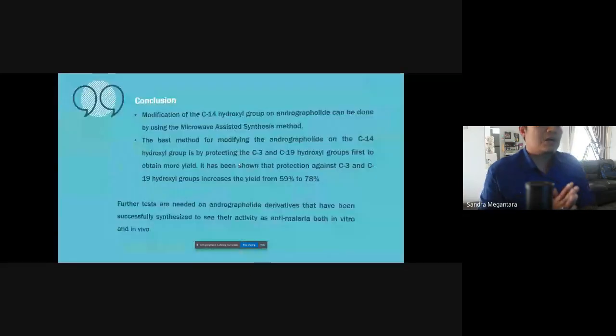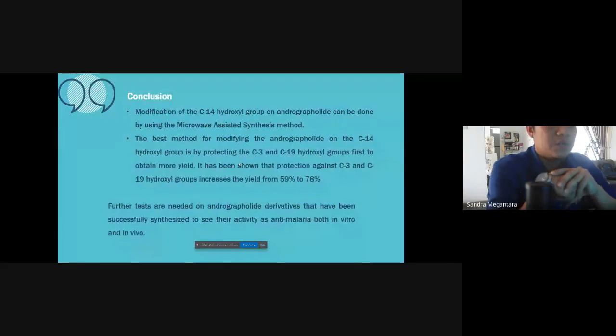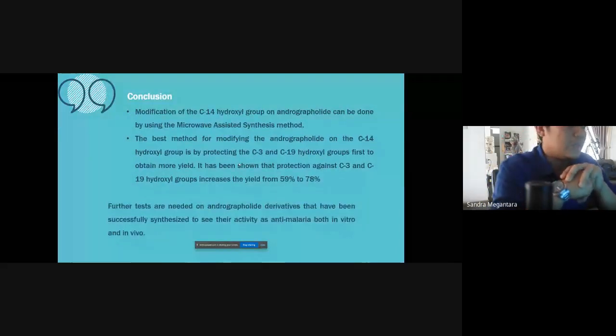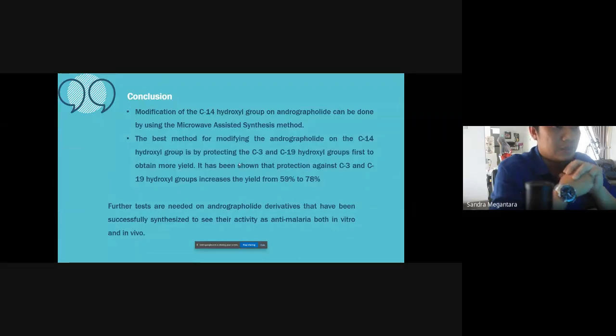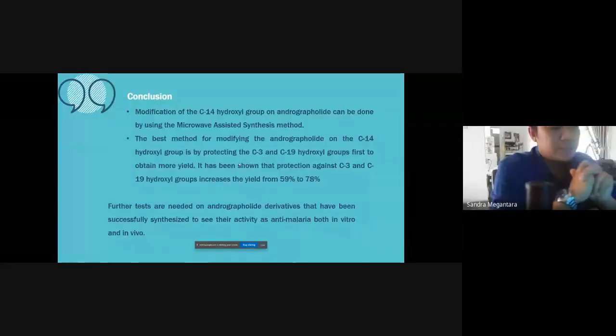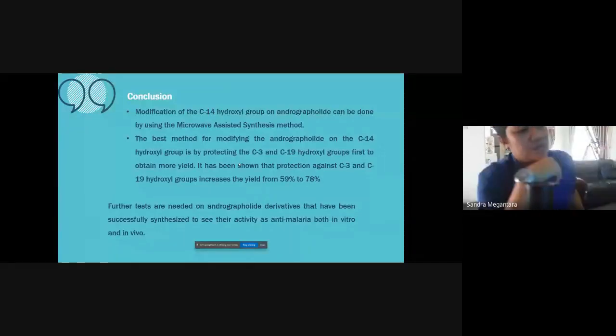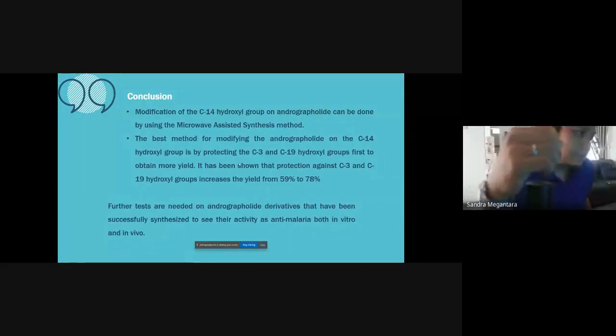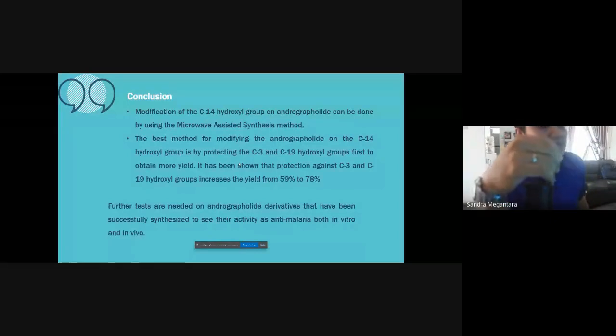And then this is the conclusion. The first conclusion is that modification of the C14 hydroxyl group on andrographolide can be done by using the microwave-assisted synthesis method. The best method for modifying andrographolide at the C14 hydroxyl group is by protecting the C3 and C19 hydroxyl groups first to obtain more yield. It has been shown that protection of the C3 and C19 hydroxyl groups increases the yield from 59 to 78%.